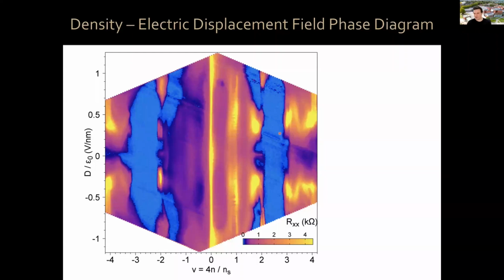Now, as you can see, this is quite a complex phase diagram. Let me guide you a little bit through it. These light blue regions are regions where you have superconductivity, and it occurs mostly between filling factors -2 and -3 and +2 and +3, but there are also these interesting branches happening there. And then yellow indicates features with high resistance, for example near charge neutrality, the typical, but also you see features for certain displacement fields at integers and so on, which are reminiscent of what happened in magic angle twisted bilayer graphene.